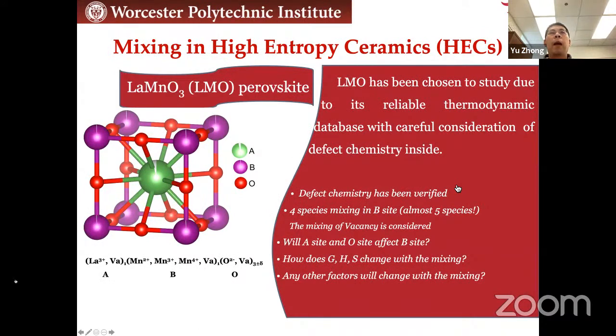Another thing I want to talk about is our recent work on high entropy ceramics. Because there is a lot of work on high entropy alloys, people say that in ceramics we should also work on high entropy ceramics. But the issue is that 99% of the researchers still follow the high entropy alloy concept. They just mix elements inside ceramics, but they don't pay attention to what is actually being mixed. Because you have different chemistry, what you mix will not be elements. What you mix will be species. We did some preliminary work to show people that what you are mixing is actually those species, and the behavior can be very different from what your intuition tells you.